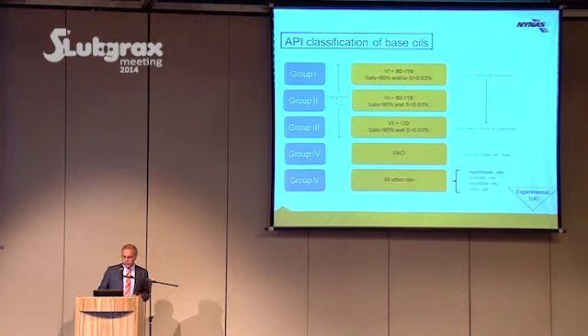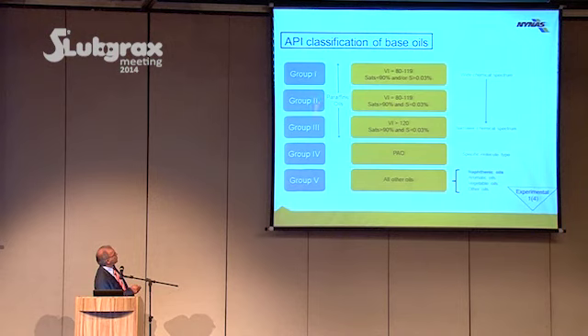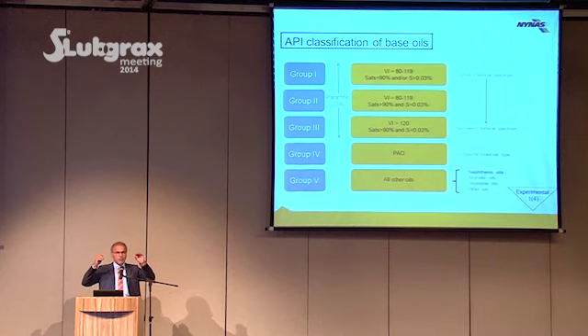A short chart, for those of you who are not aware where we belong in the naphthenic business. As you can see, within paraffinic oil, we have group 1, 2, 3. And there are, of course, several factors which separate these oils from each other. Viscosity index and sulfur content are among those. Something which is also interesting to know here is that when you move in this direction, you narrow the chemical molecules which you have, which means that the viscosity which can be produced becomes lower and lower. So for instance, you shouldn't expect any bright stock coming out from a group 1 or group 2 refinery, neither even solvent neutral from a group 3 refinery.